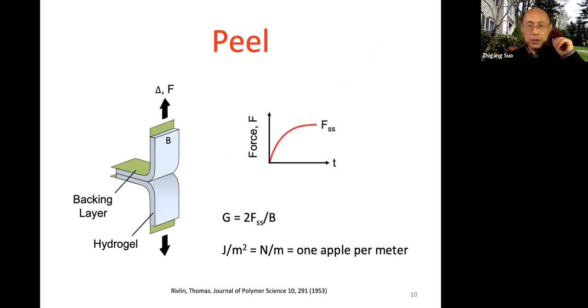I keep talking to you about this quantity, joule per meter squared. I want to give you some physical idea, but most people don't work with this quantity. Joule per meter squared is the same as Newton per meter. There are many ways to measure it. If we have a soft material, and I work mostly with hydrogel, I want to tear it apart. I use two stiff materials like plastic as backing layers, one on top and another on the bottom, and I peel it apart. This is called a peel test, and I measure force as a function of time. Initially, when the force is really small, the front doesn't move forward. You just cause more blunting. At some point, the crack starts to move steadily forward.